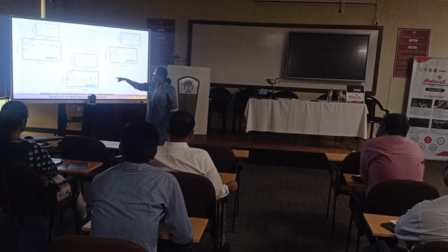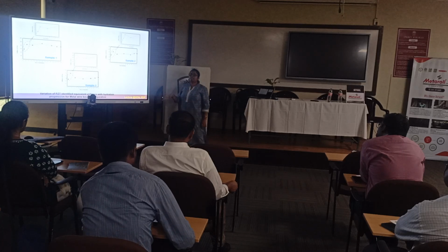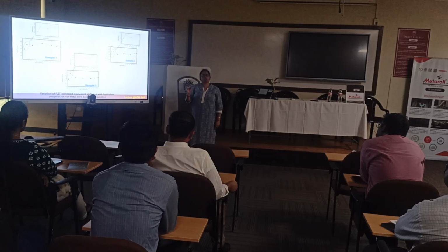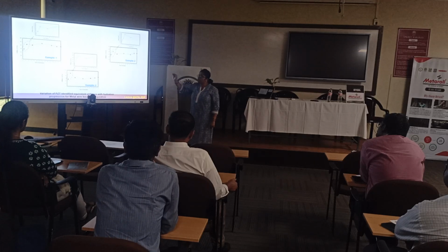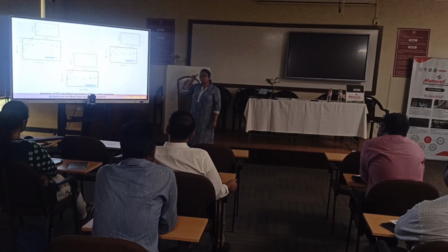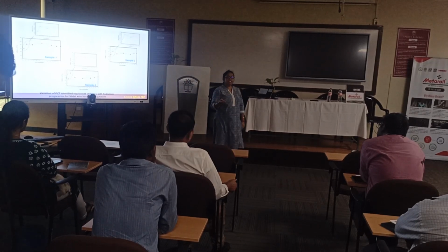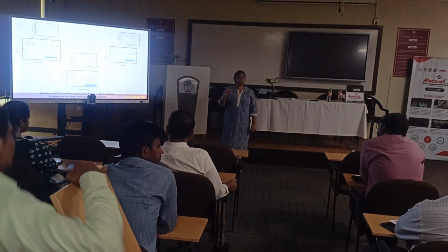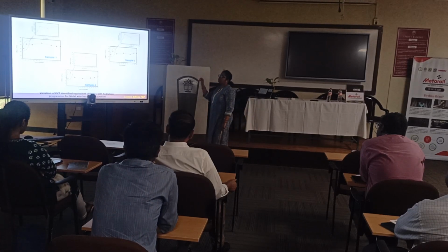After 7 days there is a stagnation or plateau in the curve, which shows that the strength development is very slow and steady, and it attains almost a constant plateau value till 28 days. This also gives you the idea that C3A reacts early, but C2S is late to react and gives the final ultimate strength in the compound.